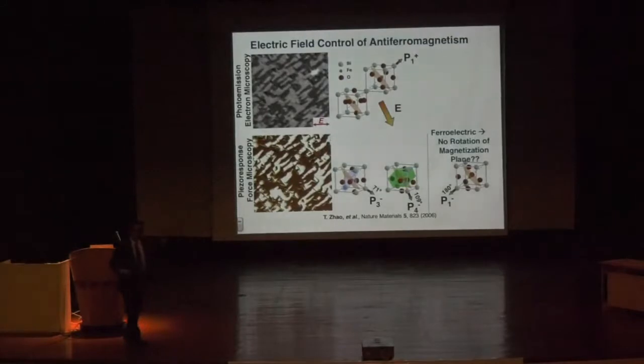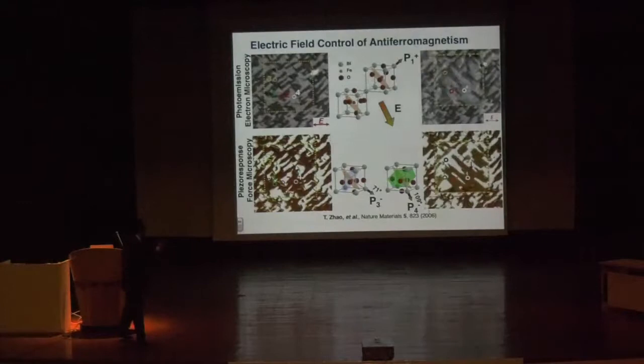Then what we did was took the same sample and applied an electric field to a small area and switched it by various different mechanisms. And we said, what happens to the antiferromagnetism? And what we found was that indeed the antiferromagnetism has changed, which is here, in response to the ferroelectric polarization, which had also changed. And so we mapped it out. We said, hey, look, when you switch the ferroelectric polarization, it looks like the antiferromagnetism is also changing. This was way back in 2006. And I don't think we really understood all of this very well. I don't think we do even now, but we have a lot better field today than we did in 2006.